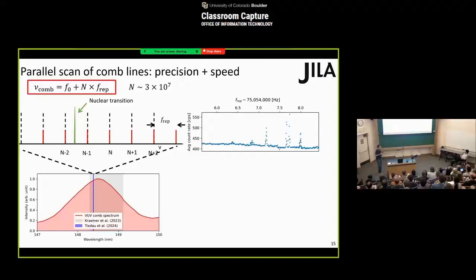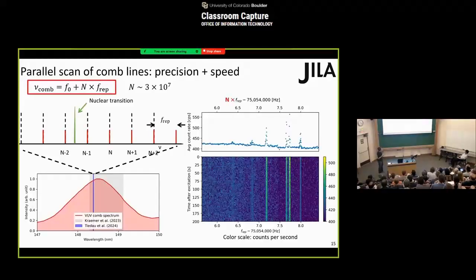So here's what we did in the experiment. We are scanning the comb repetition rate by about a few hertz. But since we have this large integer mode number n, we are covering the entire optical uncertainty region where the nuclear transition could be. In the raw data, you can see a couple of distinct spectral lines that we are highlighting in blue here. If we look at the time domain behavior of these spectroscopy features, we can see that they last for a very long time, longer than 200 seconds, which is our observation time. So these are very long-lived nuclear transitions that we are exciting in our solid-state environment.